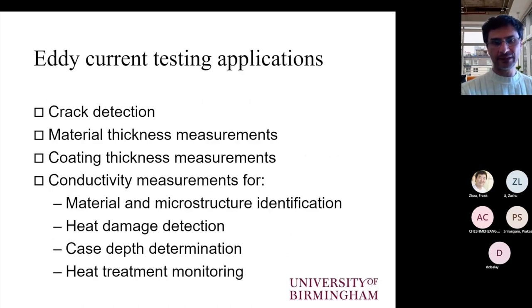The typical eddy-current testing applications include, of course, crack detection. It can be used for corrosion detection as well, and pitting corrosion. Material thickness measurements, which are related to corrosion, erosion, as well as for geometrical analysis. Coating thickness measurements. So, for example, in steel turbine blades, we have special thermal barrier coatings that are almost impossible to inspect in some cases. And one way of doing this inspection is by applying eddy-current testing, because the degradation of the thermal barrier will result in some changes in the relative magnetic permeability, to which eddy-current testing will be extremely sensitive. So if we are picking up permeability-related variations, that means that our thermal barrier coating is degrading, and that can be quantified actually.